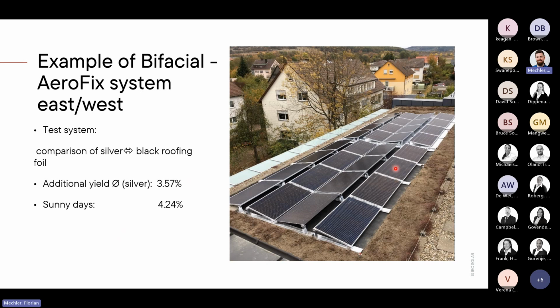And the last thing we tested with bifacial modules is what is the different additional yield when you use silver foil on the ground in Aerofix or black foil on the ground. And this is also very interesting to see the different albedo effects. With a silver foil, you get roundabout 3.5% more additional yield in comparison to the black one. And at sunny days, it means up to 4.2% additional yield. So also for flat roof applications, it makes really sense to go with a bifacial module.